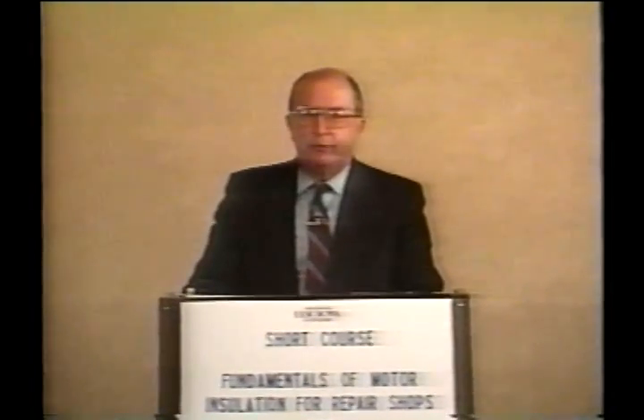But at the same time, on the maintenance of the properties of the resin, the polyesters have traditionally been controlled more easily than epoxies. Now, two of the key properties that must be maintained in the resin system for vacuum pressure impregnation is the viscosity of the resin and its gel time. The viscosity is important, as we've already said, because the more fluid the resin, the more able it is to penetrate through the multiple layers of material and get inside and do its job.